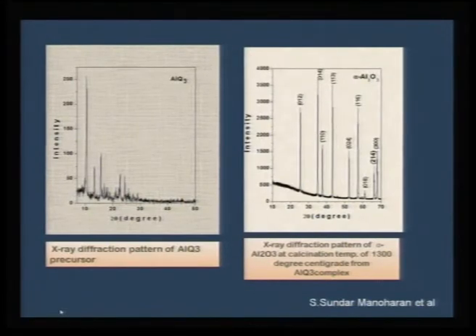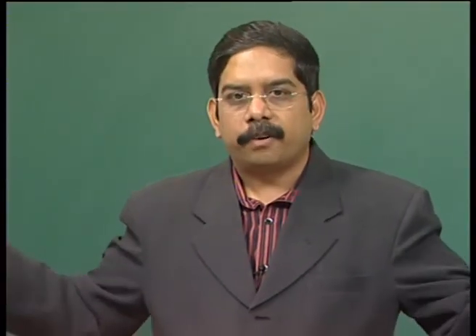Indeed, in this X-ray pattern we see the same thing. AlQ3, as you see, is the precursor, and on decomposing this I get a very highly crystalline single phase Al2O3. And the beauty here is I am not getting any other phases of alumina other than the alpha phase, which is a high temperature phase, and this high temperature phase oxide cannot be formed through other routes without heating it to 1400 degrees C. As you would see from the thermogravimetry, these compounds can be prepared as early as 600 degrees C. There is no need for you to even go up to 1400 C.